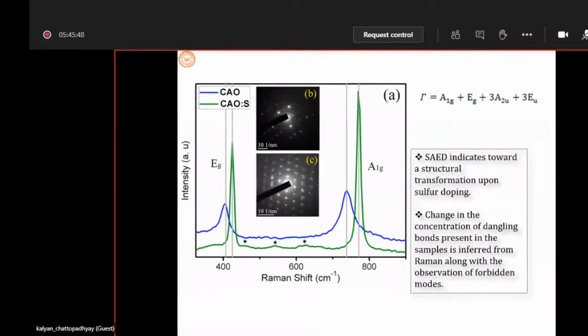And these are the Raman and TEM results. It is very interesting. If you remember, our DFT suggested some changes in the symmetry of the system. Now, panel B is basically a pristine SAED pattern, and C is after sulfur incorporation. You can clearly see that the symmetry got changed, which was also predicted by DFT. Raman is also equally interesting.